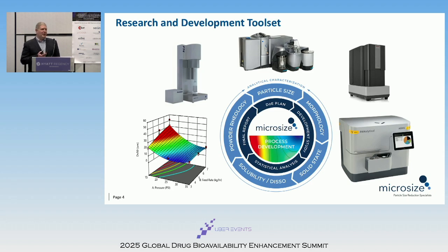And then the third theme of that lab is powder flow. So we have an FT4 powder rheometer, as well as bulk and tap and angle of repose. We implement DOE studies at the site using STAT-EASE software. And with the addition of the solubility company, now we can offer a novel way to measure solubility and dissolution. And this will help us judge what kind of particle size we should be targeting to make sure everything is dissolved in the time that it needs to be dissolved.